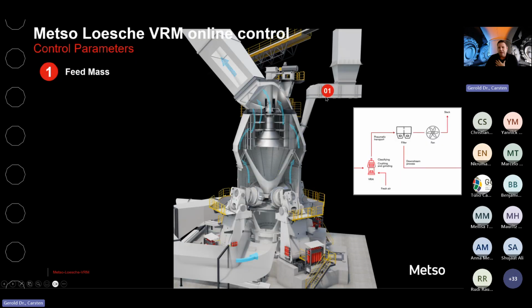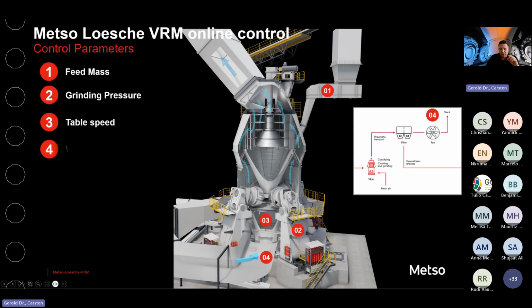Speaking about the mill, we can precisely adjust the feed amount to the mill. We then have the grinding pressure, which together with the table speed defines how efficiently the comminution is happening. That is one of the force pairs that we have. The other is the volume flow, shown by these blue arrows to the top. You can imagine a suction to the inside of the classifier. So this is one force. The other force is the centrifugal force created by the classifier RPM. The faster the classifier turns, the higher the centrifugal force to the outside. So in normal operation, when you just change the classifier RPM, you also change your product particle size.